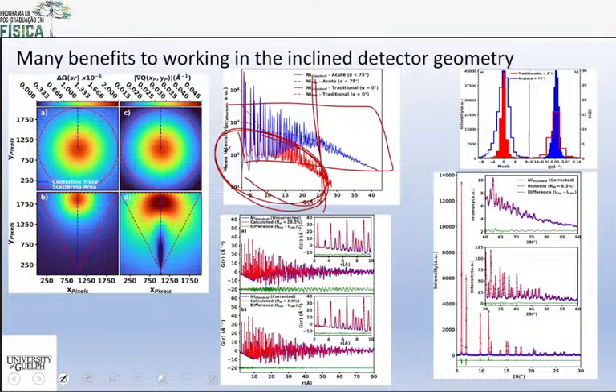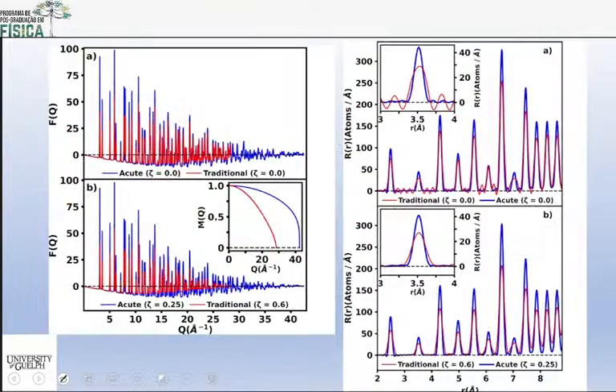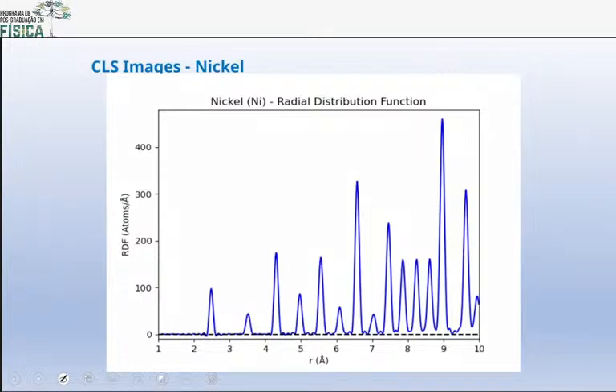Okay, so this picture here, do I have another picture? This one's better. The bottom line is, and if you're zoning out, focus now. This picture on the right is what's important. And that's our histogram from a sample of nickel. And when we set up our geometry correctly, we get this blue curve here. And what you see is it's sharper and there's no noise. We get really high quality data. That's our nickel. So this is our nearest neighbor, and we have no background. See, it's clean.